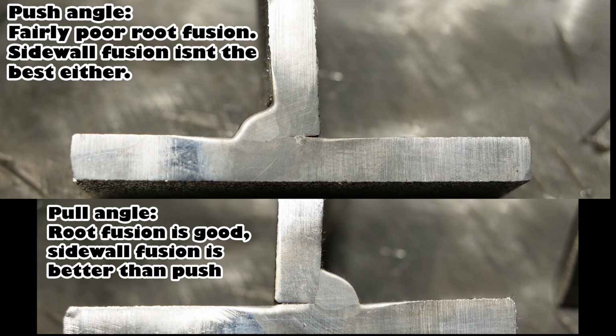So here where we look at both of them, you can see there's a definite difference. No doubt the pull is roped up a little bit more. Maybe I went a little bit slower and it deposited a little bit more metal. But again, there's more root fusion in it. The penetration in the sidewall is better. It's subtle, but it's there.